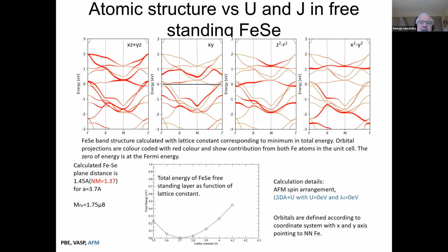In, for example, lanthanum cobaltate, okay? So whether you have a local moment matters much more than how it is actually ordered. And that's what I want to show you. So this looks very, very strange. This band structure is completely different now. There still is a hole pocket and an electron pocket, although at the M point, it seems that the electron pocket has disappeared and you only have a hole pocket, okay? And you have this strange band, which is almost flat, crossing very close to the Fermi energy. And the magnetic moment is distributed all over the place.